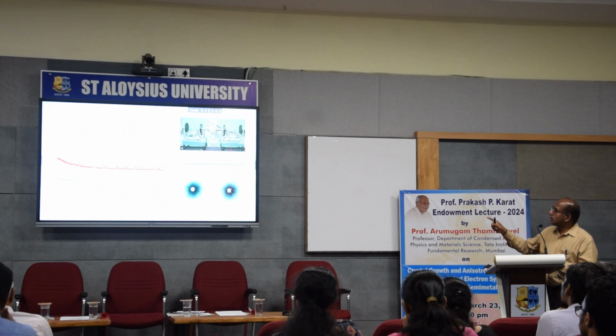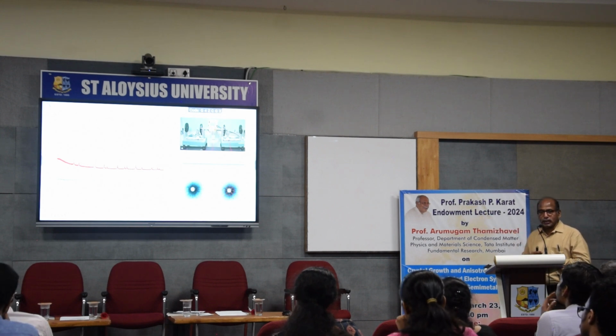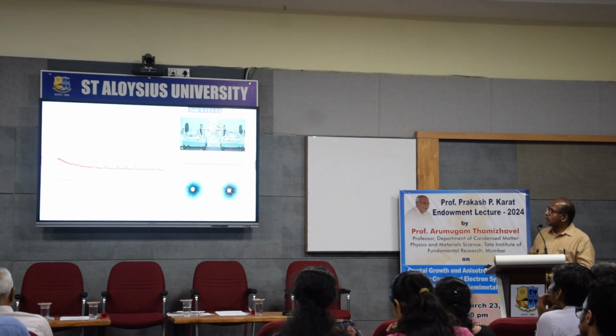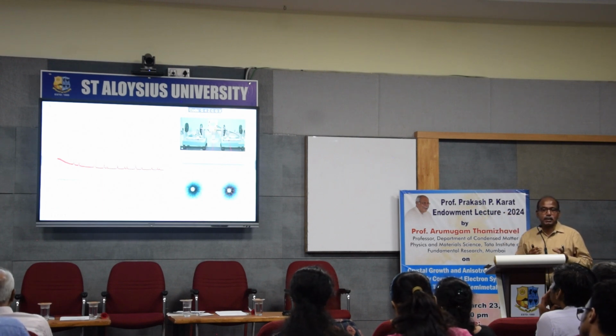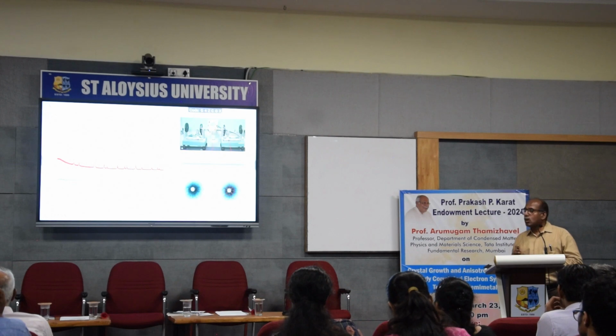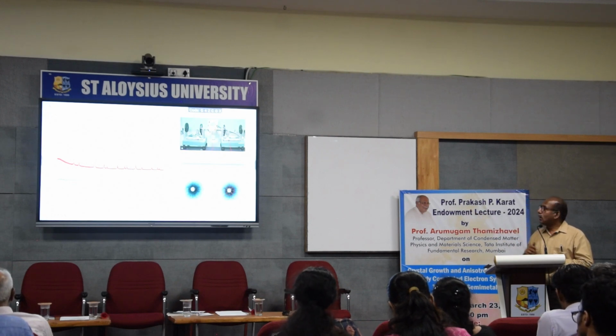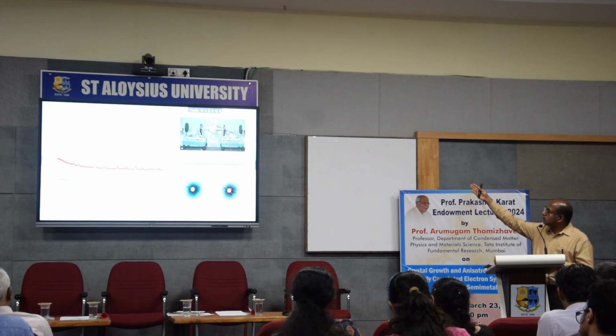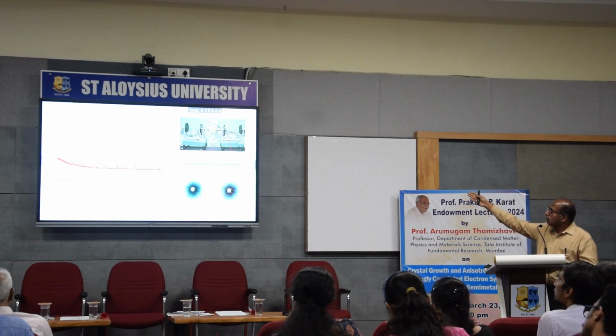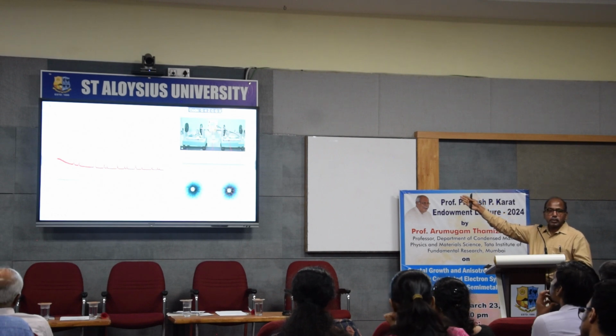Before I did the Laue diffraction, I also did a powder X-ray diffraction, and I found out the phase purity. That means whether there is any impurity phase, whether there is any unreacted cerium or unreacted magnesium or any other composition of cerium magnesium formed in my sample. All those things can be confirmed from the powder X-ray diffraction. And on the other hand, if I do X-ray diffraction using that instrument which is shown above, it uses a polychromatic source of X-ray.